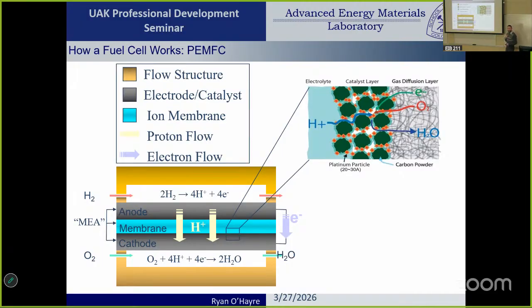So just for reference, how thick is this section that has the platinum? Yeah, great question. Typically this thin catalyst layer is on the order of microns, 5 to 30 microns. The carbon electrode is going to be 300 microns or so, half a millimeter at the most. The electrolyte membrane is typically nowadays like 25 microns, 25 to 50 for the polymers. For the ceramics, we can actually get down, and we need to because ceramics are less conductive, down below 10 microns nowadays, the state of the art. So those layers are all super thin.